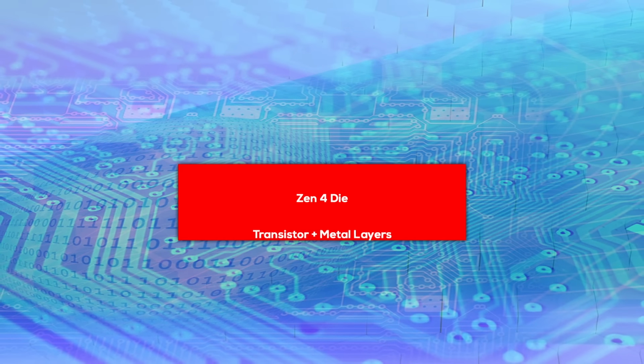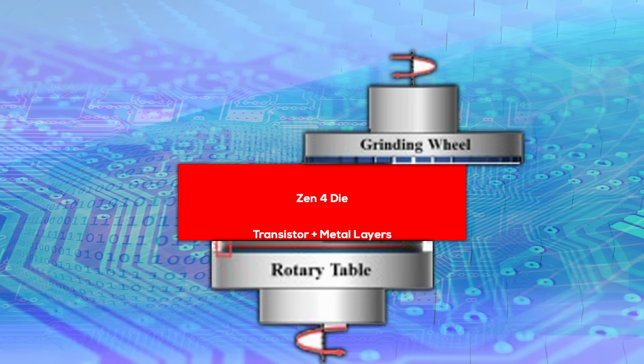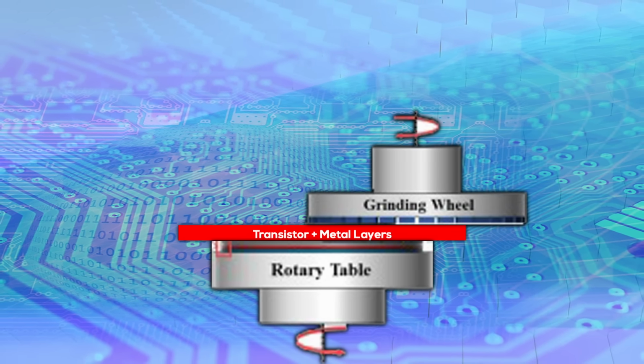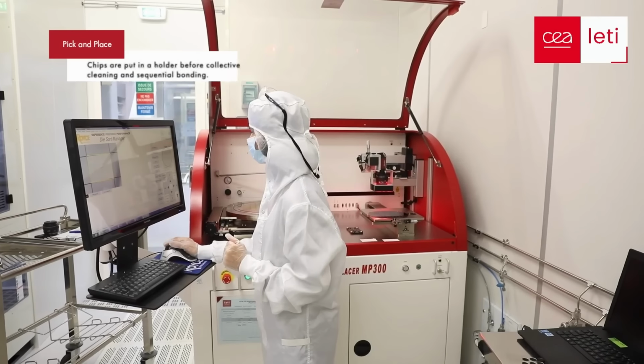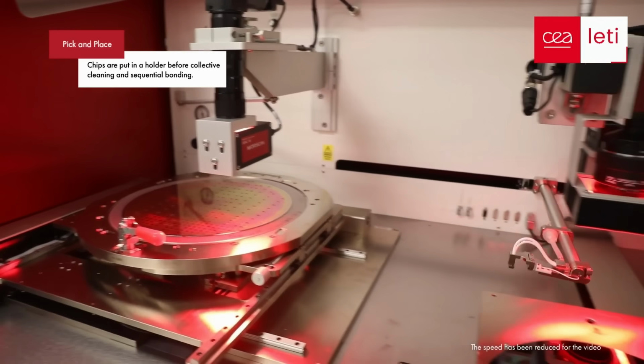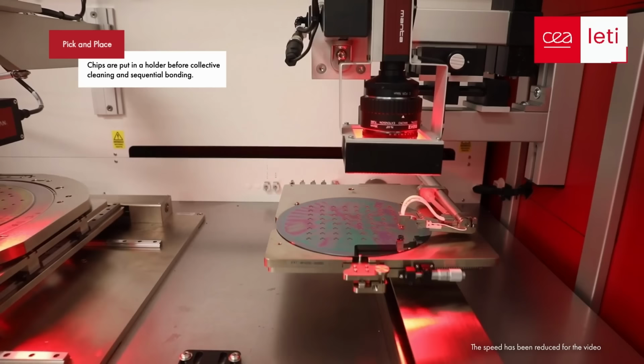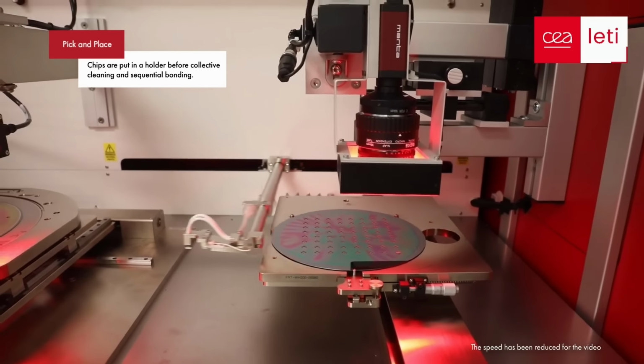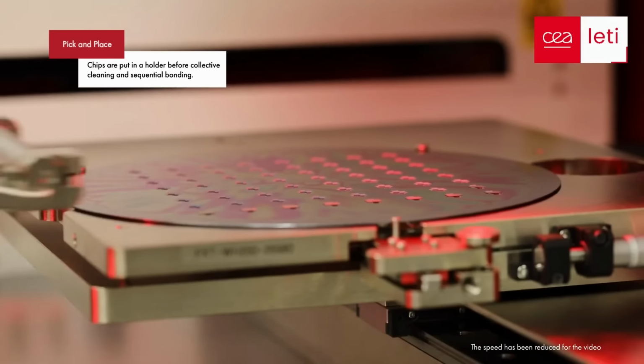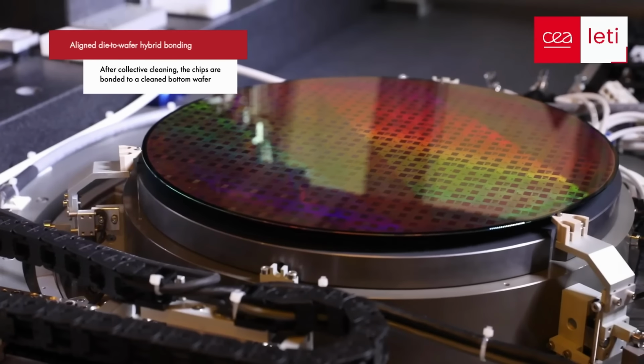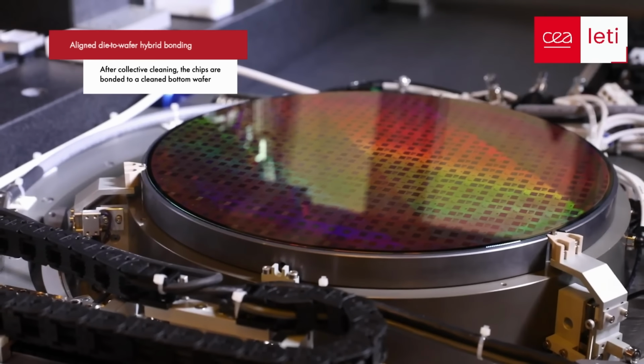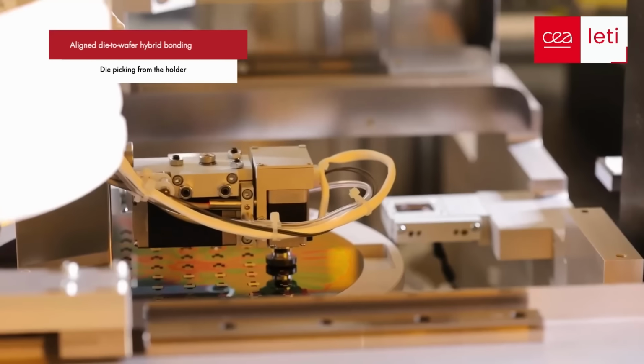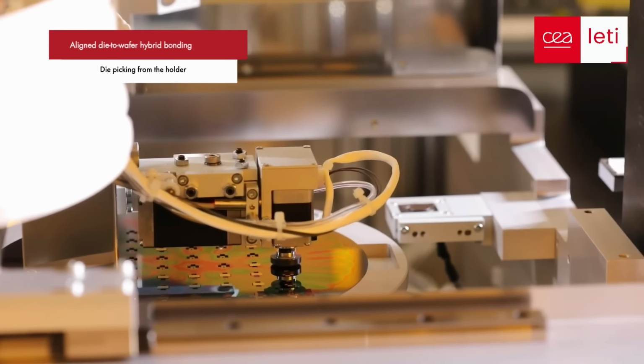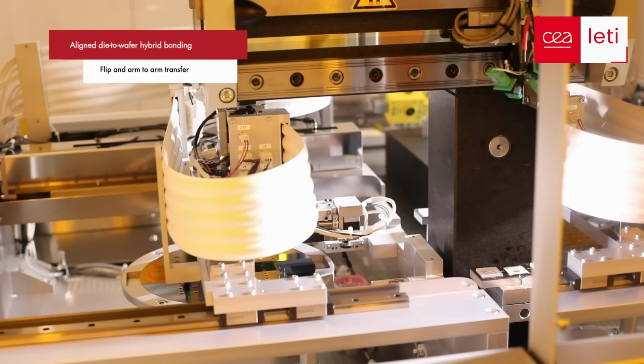The result of that wafer thinning process is that we have super thin Zen 4 CCDs that are little more than transistor and metal layers, sitting on top of a carrier wafer. Next, we have to prepare the 3D V-Cache. Because the cache chiplets are smaller than the CCDs they will be bonded to, they also have to be placed on a carrier wafer for bonding. First, to align them properly. And second, if TSMC were to press different sized chips against each other, they would most likely break. That means both chips that are being hybrid bonded via two wafers have to have the same surface size. The reconstituted carrier wafer has to be a combination of the 3D V-Cache chiplet and the two small pieces of structural silicon to achieve the same surface area as the CCDs.